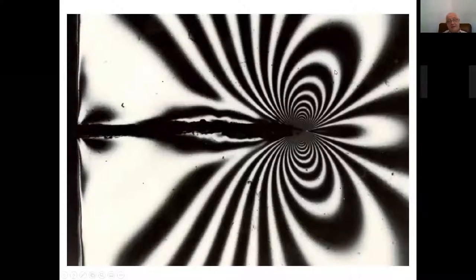Okay, so let's talk a little bit about 2D photoelasticity. First of all, I'm showing you a good picture with a crack and fringes around the crack tip. The crack tip, of course, is about here. You have some blunting of the crack. This is a transparent photoelastic material, and you have these fringes. The order of the fringe can be counted. This is the locus of the difference of the principal stresses being constant. We are going to talk about this a little bit later.